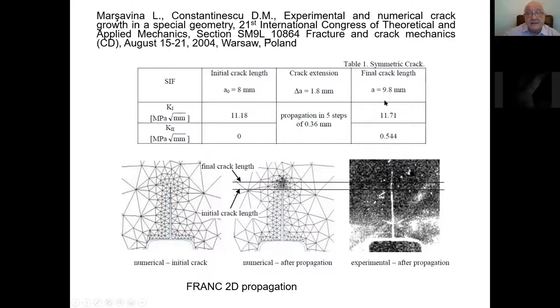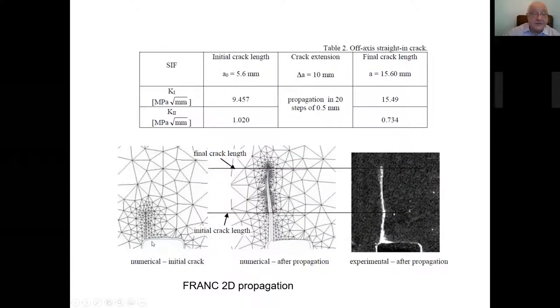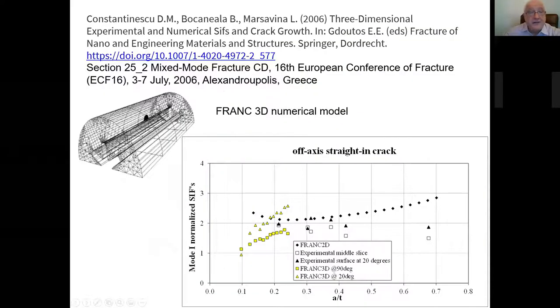We had quite a good comparison, at least from the point of view of crack shape after propagation, from the initial crack towards the final crack. Or later on, if moving towards this off-axis straight crack, again, things don't look too bad. Still having some mode 2 after propagation, but this, of course, is very small compared to mode 1. For 3D measurements and for 3D numerical simulation, we used Franc 3D some years ago. And I would like to point out this comparison of results, because this is quite interesting.